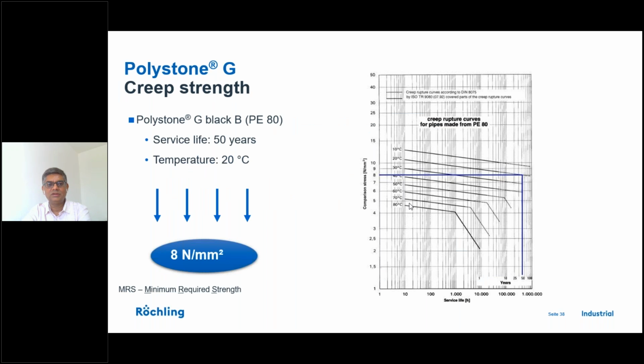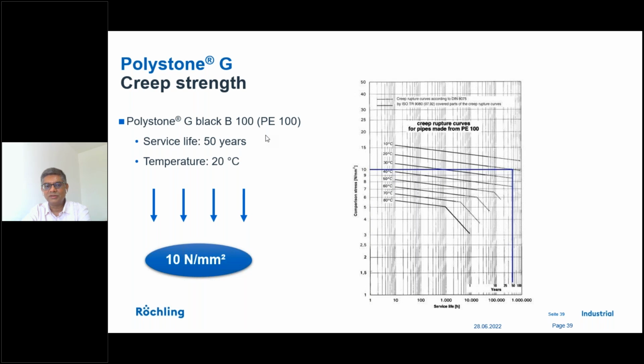Similar creep curves, this is PE 80, where you have 8 Newton per mm square, whereas more recent materials like PE 100, which is used for the chemical industry, is 10 Newton. But again, here I can tell you that there is a general perception that if it is for the chemical industry, we need to use PE 100. Well, yes, it is applicable for certain conditions, but not 100 out of 100 conditions.